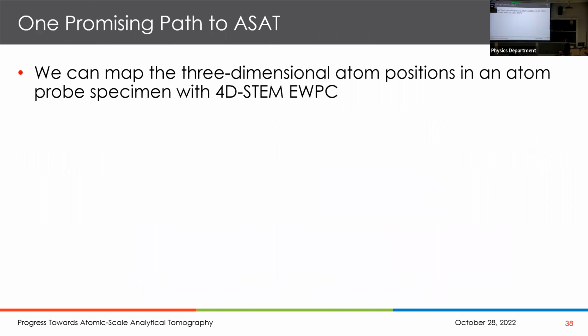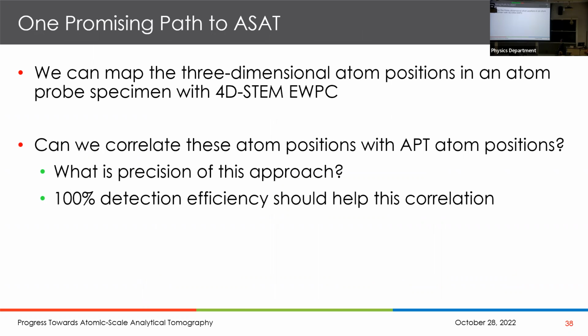And so this does suggest that it is a promising way to achieve atomic scale analytical tomography, so that we could map these three-dimensional atom positions using the 4D STEM exit wave phase power spectrum. And then the challenge, and we don't have this all worked out yet, this is where you now know where we're at, the bleeding edge: can we correlate, with zero error, if you will, the atom positions that we've just determined in the electron microscope, then we rip the specimen apart in the atom probe? Can we put those two together?